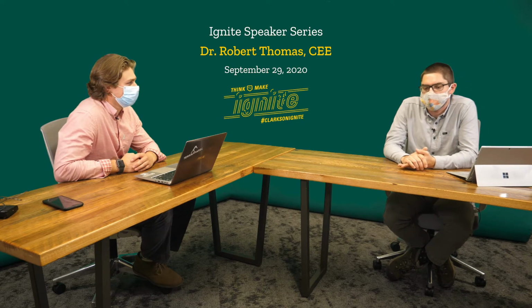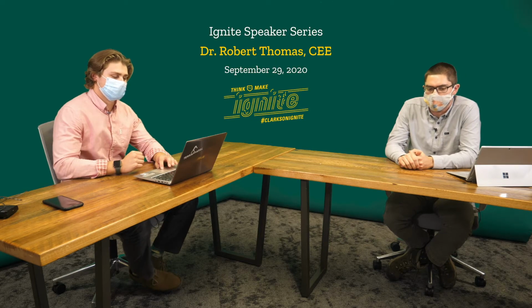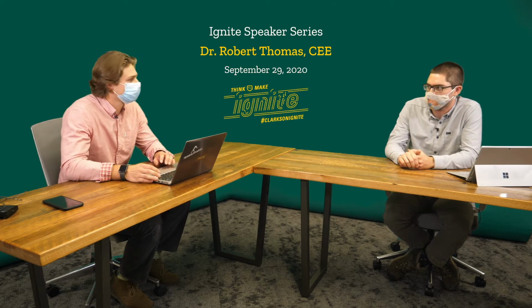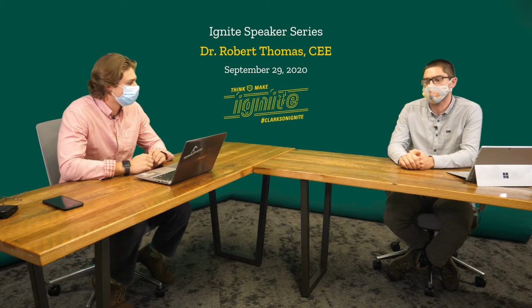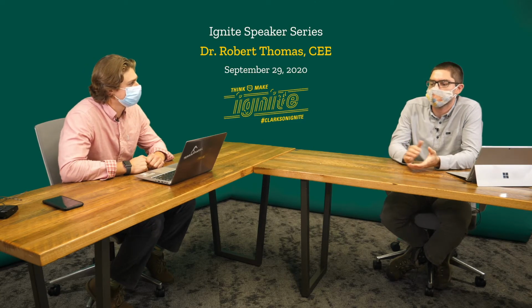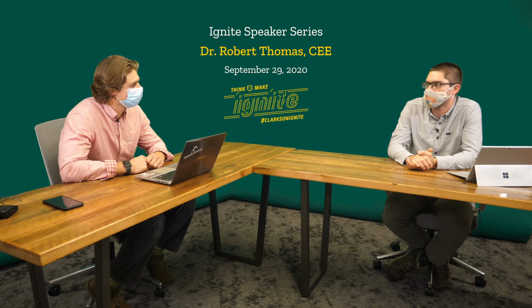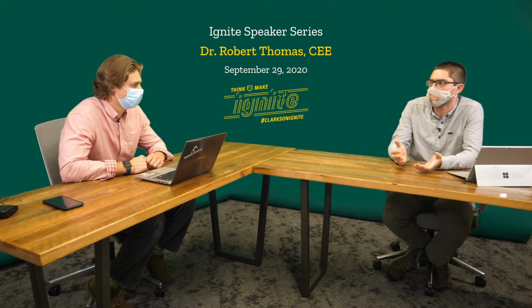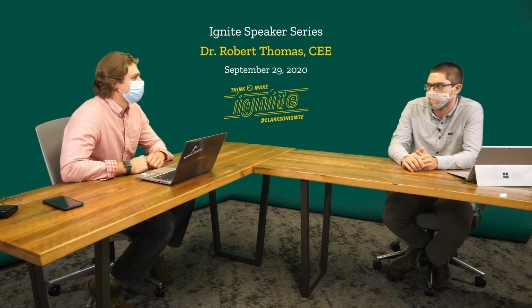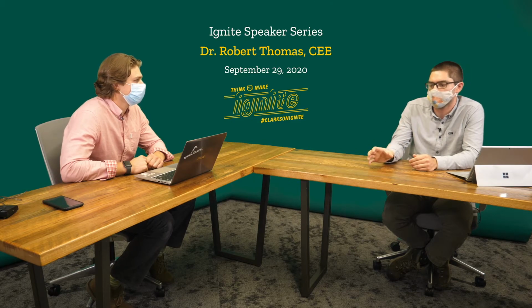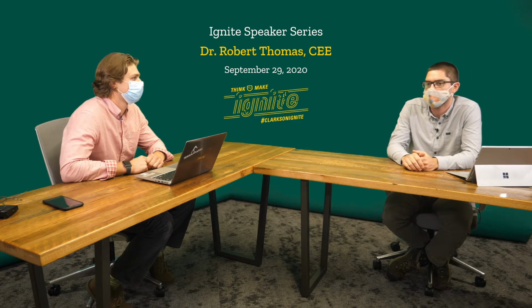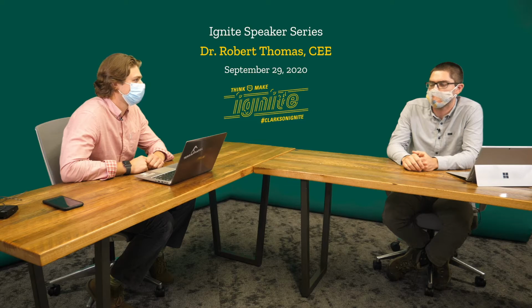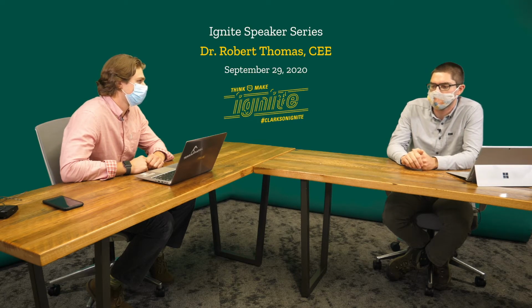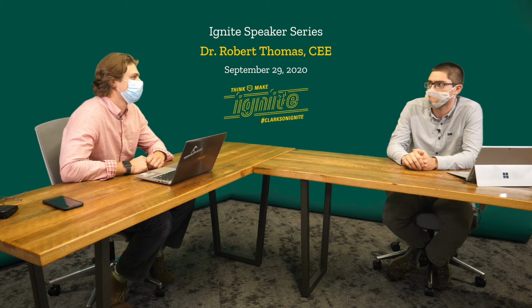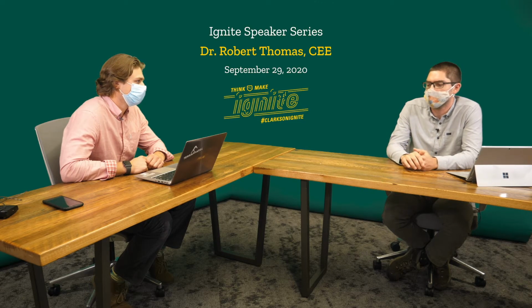One of the policy restrictions we're used to is, let's go back to fly ash for example. Because we've been using fly ash for so long, one of the major hurdles is that we've been restricted by code to like 40% of the total cementitious material. So 60% Portland cement, 40% fly ash. We've got research that says we can up that to 80% fly ash. If we use a process called alkali activation, we can up that to 100% fly ash. But the codes don't allow us to do that.